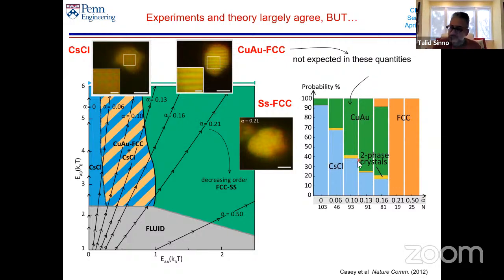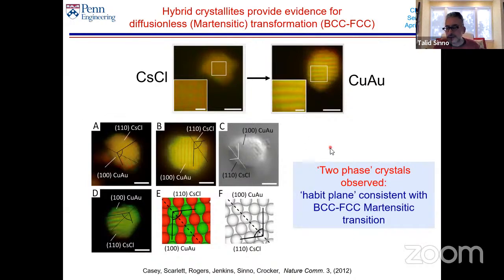If you run simulations, we can get roughly this picture, but the problem is we never see this perfectly ordered copper gold because of what I just told you, because of defects. Defects kill perfect ordering, yet the experiments show perfect ordering. And so this was kind of a mystery, and it's one of the topics that I'm going to talk about today. And it turns out that these copper gold crystallites don't actually nucleate homogeneously. What happens is that crystallites grow cesium chloride and then undergo a martensitic transformation to copper gold.